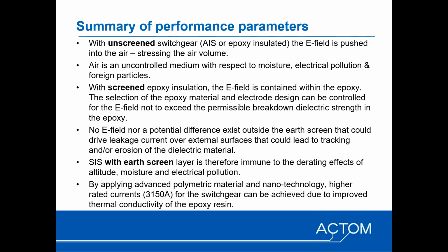In summary, with the unscreened switchgear, typically AIS, and even unscreened epoxy insulation, the electrostatic field is pushed into the air, stressing the volume of the air. The air is an uncontrolled medium with respect to moisture, electrical pollution, and foreign particles. Where you have screened epoxy insulation, the electrostatic field is contained within the epoxy, and by selecting your epoxy material properties and your electrode design on the inside of that epoxy, you can actually control the electrostatic field appearing, so as not to exceed the permissible breakdown strength of the epoxy.